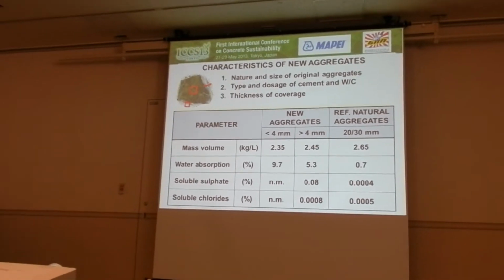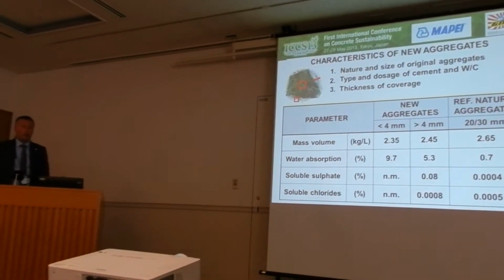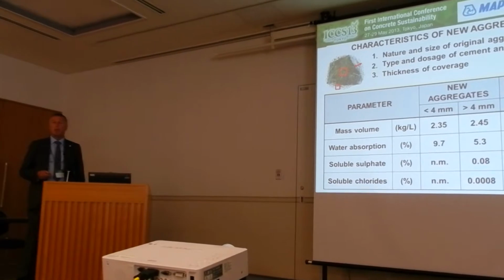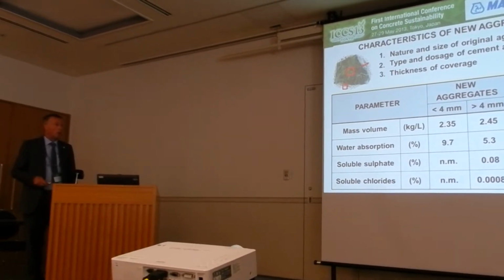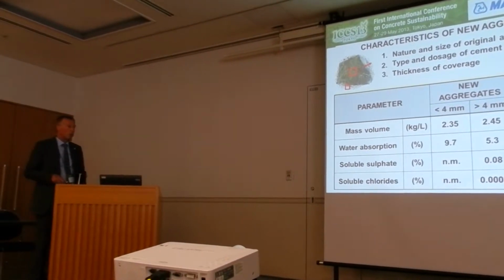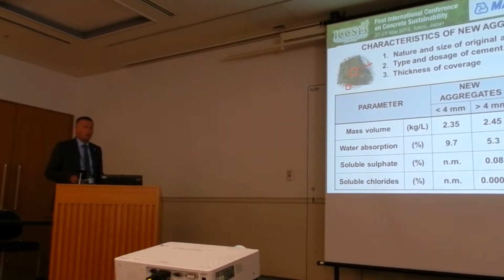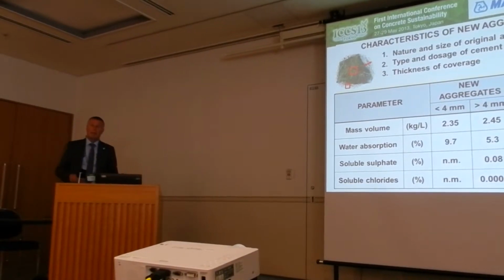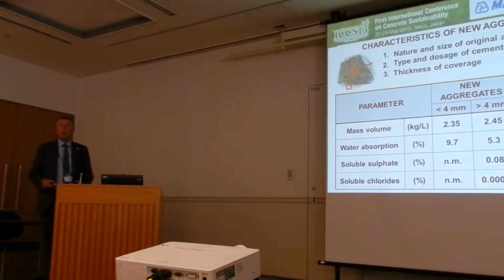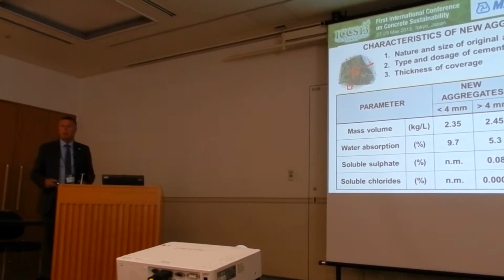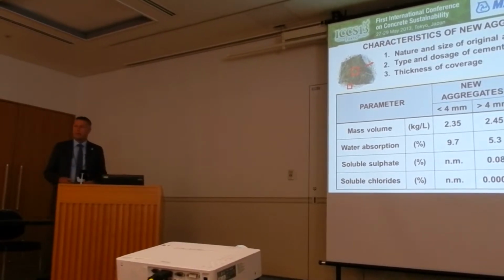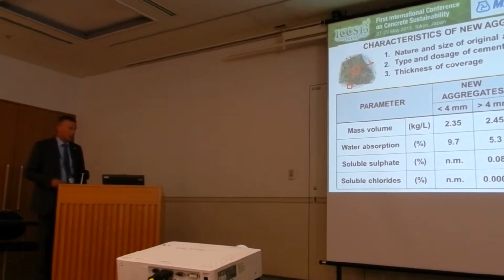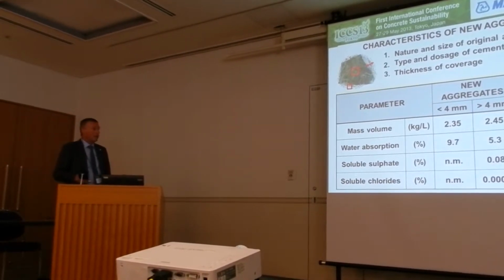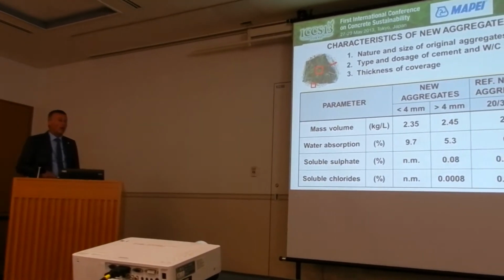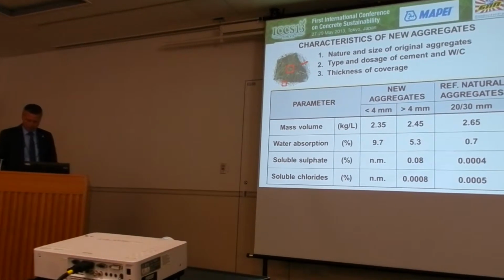sulfate, and so the typical level of sulfate is increased compared to a natural aggregate without sulfate, with very low content of sulfate. By the way, the increase of sulfate content is not so high, and it is still quite below the technical standard, for instance, stated by the European technical standard. And there is no increase of other components such as chloride.